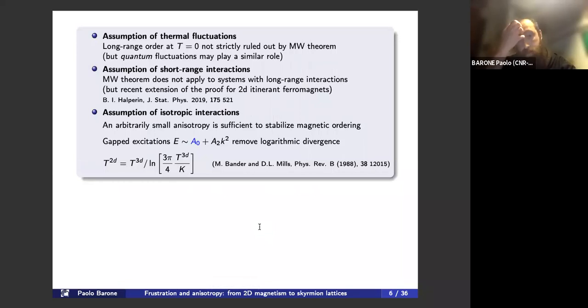Now let's review for a second the assumptions behind the theorem. First of all, we are looking just at the role of thermal fluctuations. So the Mermin-Wagner theorem doesn't tell anything about the ground state at T equals 0, even though in that case one should include also quantum fluctuations. The second important assumption is the one of short-range interactions. So in principle, the original proof does not apply to itinerant ferromagnets, even though quite recently the proof has been extended to include those systems. So it may not be enough to have long-range interaction to guarantee a two-dimensional long-range magnetic order.